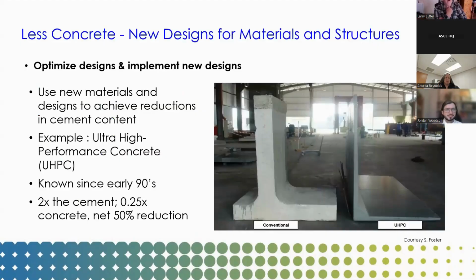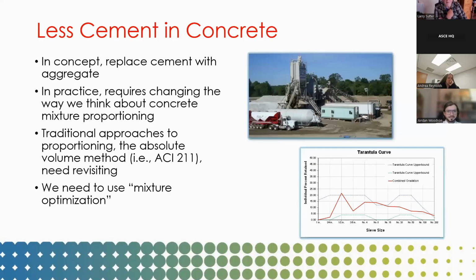Next slide. So we talk about new materials. Here's one example I like to use. This is two structural members, one on the right made with ultra-high performance concrete, one on the left made with conventional concrete. Ultra-high performance concrete probably has 2 to 3 times the cement we normally see in concrete. However, we use a quarter of the concrete to make the structure, so the net result is approximately 50% reduction in cement. So these are two structural members that perform the same.